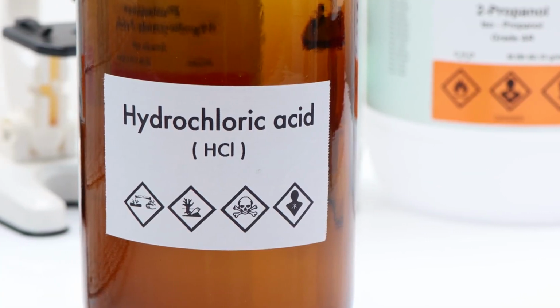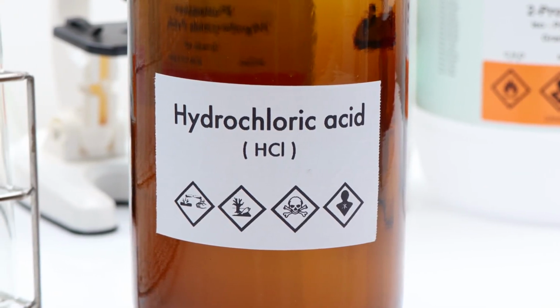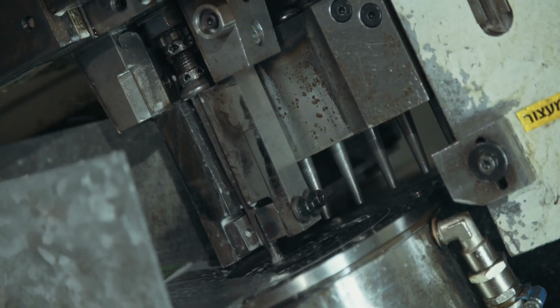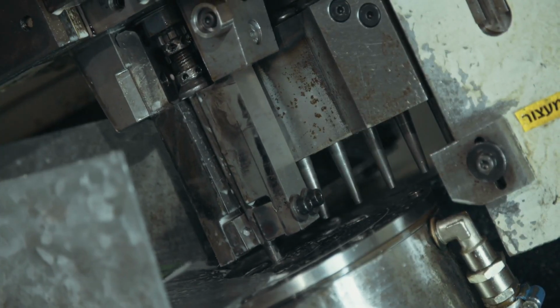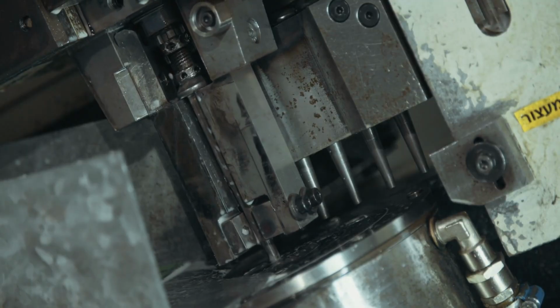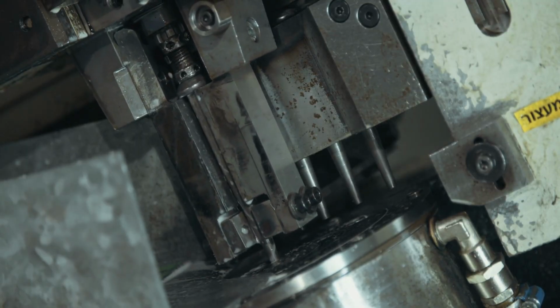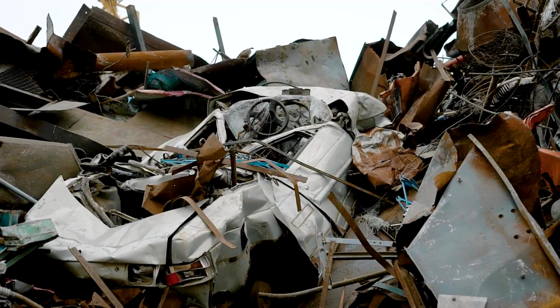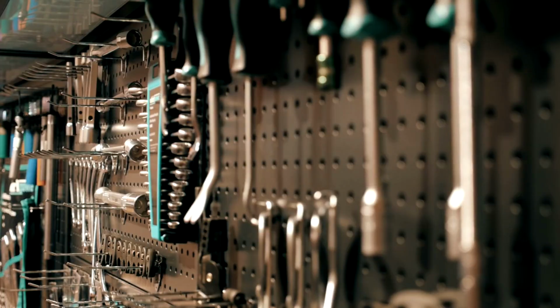When you soak a tool in hydrochloric acid, yes, the rust comes off, but the acid also attacks the underlying steel, etching pits into the surface, thinning the cross-section, and weakening the metal. You remove the disease by poisoning the patient. The tool looks cleaner but is structurally compromised.